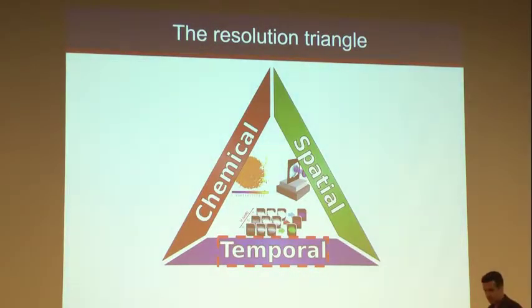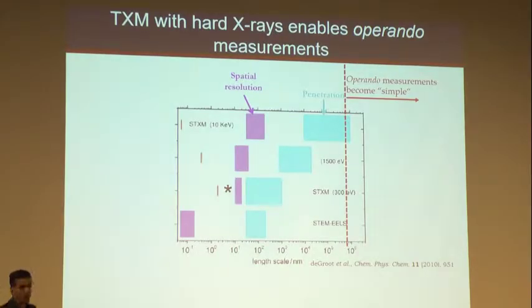The last side of the triangle is time resolution. This is self-explanatory. We're doing a reaction. Reactions evolve with time. How do they evolve? Back to the plot that I showed you before, if you think in terms of how you're going to build a reactor that you can get signal in and out of to be able to measure this, well, this is a plot of penetration depending on the X-ray radiation that you're using. And so in the hard X-ray regime, you're penetrating through scales that allow you to start building cells with electrolyte and separator and lithium and still be able to get your beam through to get a transmission signal.